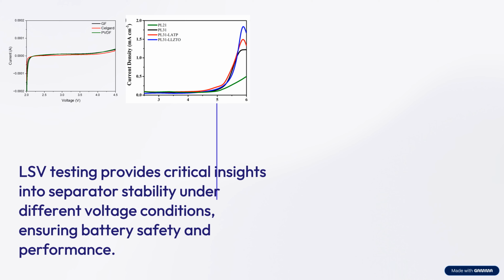And you have also seen these kinds of graphs where it starts from maybe 2.5 volt and goes up, and when it goes up beyond 5 volt, actually it's decomposition of electrolyte. A lot of electrolytes decompose after 5 volt, or they may also react with the separator, but most of the separators are neutral because they are polymers, and this is because of decomposition of the electrolyte. So if you see these peaks before 4 volt or before 5 volt, it means the separator is reacting.